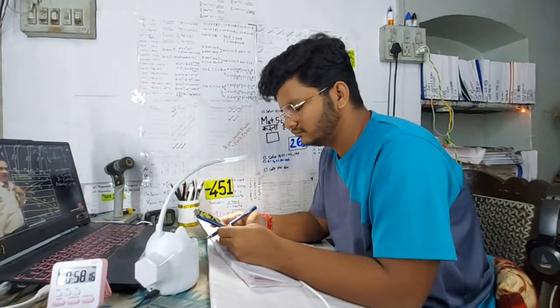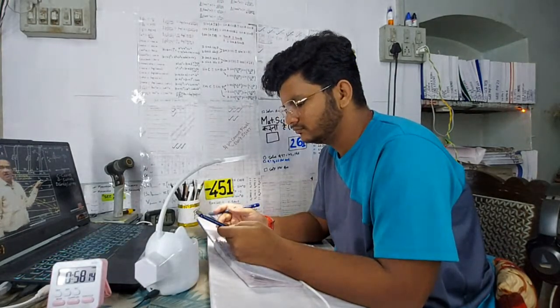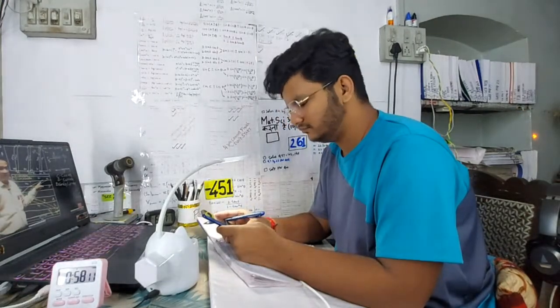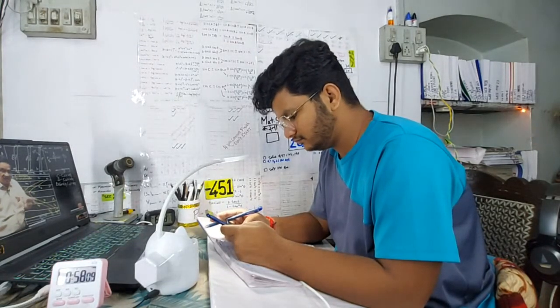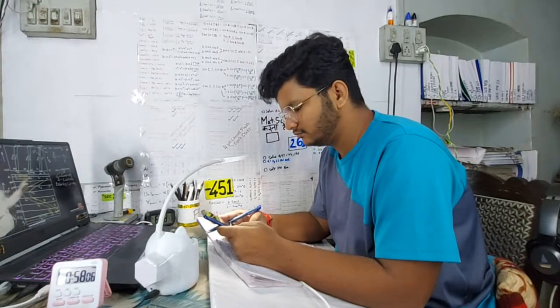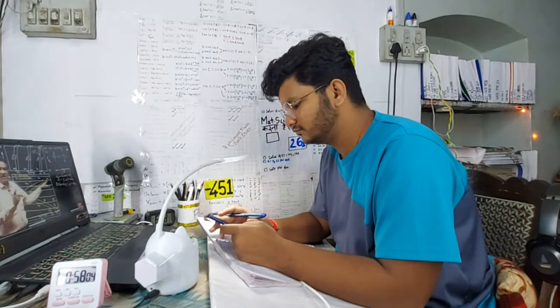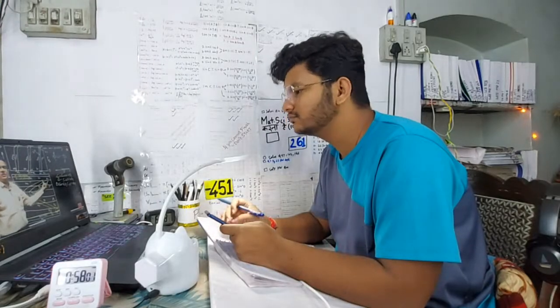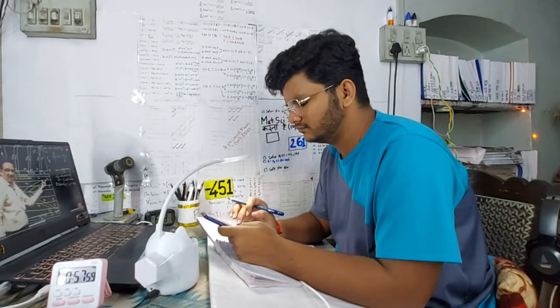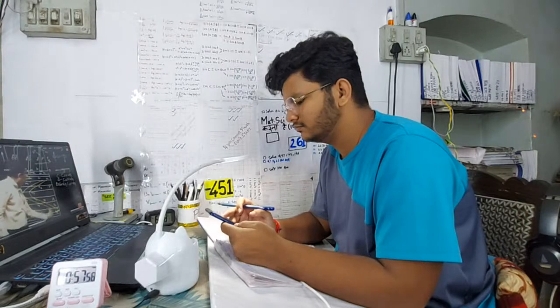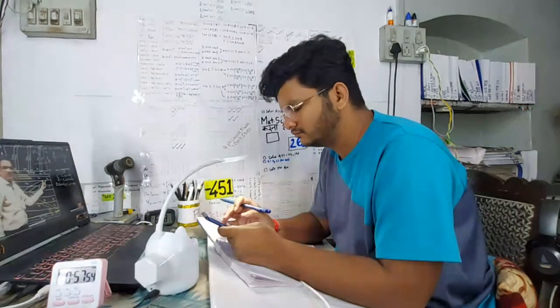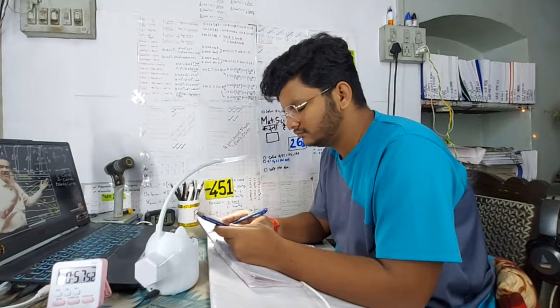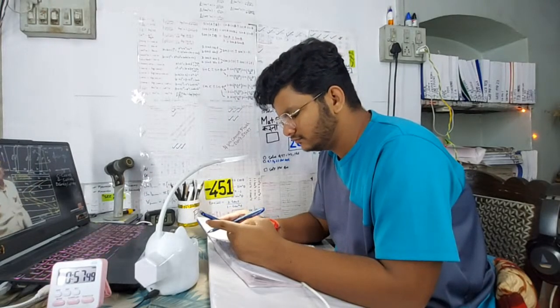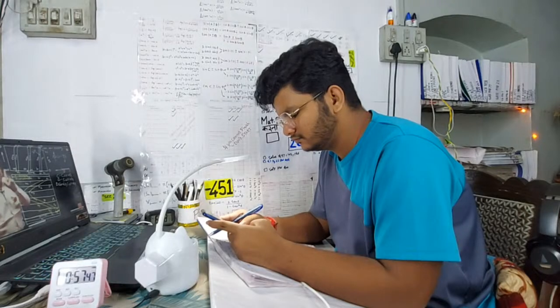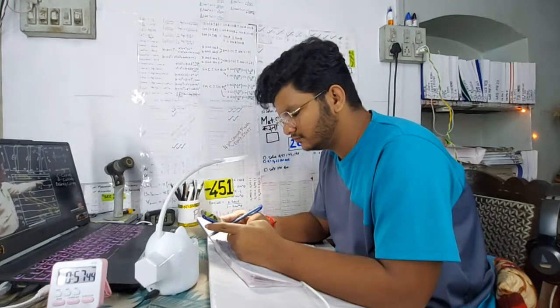Usefulness of this diagram is, tell me, at 700 degrees centigrade, what is B1? Beginning time of austenite transformation into pearlite. What is E1? Ending time of austenite transformation into pearlite. बोलो बेटा, at 700 degree centigrade तुम्हारे पास beginning time है, ending time of transformation है. So if you project this B1 E1 distance onto x-axis, ending time minus beginning time of transformation gives you time taken for austenite to transform into pearlite at a constant temperature of 700 degree centigrade.